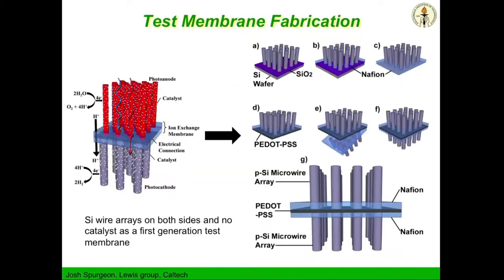And what we do there is we grow a set of bottom rods, peel them off, grow a set of rods that will be on the top, peel them off, and then intervene with a conducting polymer that also passes protons, that also makes ohmic electrical contact between the top rods and the bottom rods. Just to show that we could do this, because if you were in the photovoltaic industry, and you had to grow epitaxially a layer on the top of something and a layer on the bottom of something, you would have to use metal organic vapor phase epitaxy or molecular beam epitaxy to lattice match every atom on the second layer with the layers on the top. And that would be very expensive.